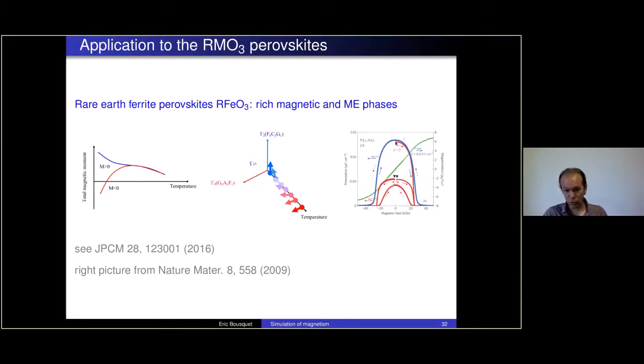And what I show also is that the gadolinium ferrite is also magnetoelectric. So here at zero applied magnetic field, you have a non-zero polarization. And when they start to apply a magnetic field, here we look at the blue curve, the polarization starts to decrease non-linearly up to zero. But the modification of the polarization here is quite large. It's much, much larger than what you can observe in chromium oxide, for example. And then we wanted to simulate that at the end.